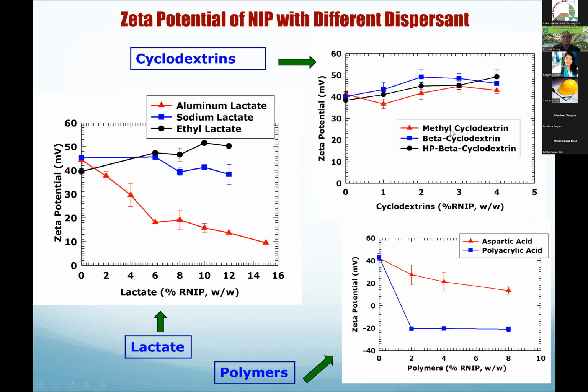And here with the cyclodextrins, you see there's not much change in the surface charge, zeta potential. They're all slightly increasing it. And then you look at these two acids. The two acids are showing a decrease in surface charge, and this polyacrylic acid is showing significant lowering of the surface charge and actually changing the surface charge from positive to negative. So this is how we find it.